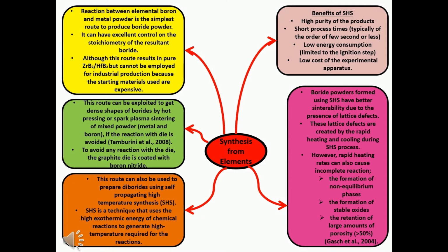Synthesis from elements. Reaction between elemental boron and metal powder is the simplest route to produce boride powder. It can have excellent control on the stoichiometry of the resultant boride. Although this route results in pure zirconium diboride and hafnium diboride, it cannot be employed for industrial production because the starting materials used are expensive.